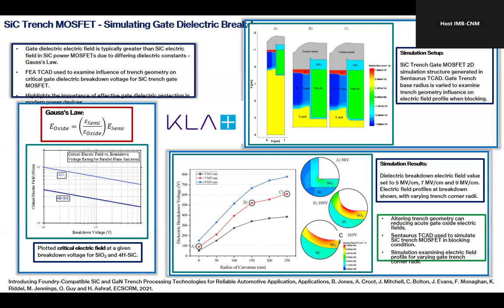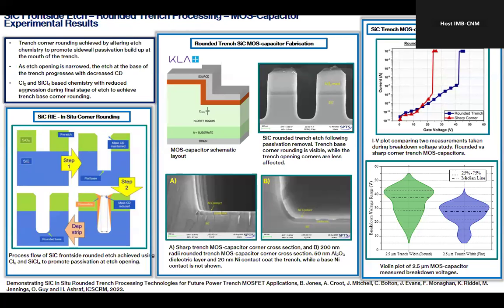So this was a good study, and we backed this up with fabrication. We used our tools to fabricate a nice sharp corner versus a nice round corner, you can see probably this image is the best here. I think we used the deposited oxide in this case, yes, 50 nanometers of aluminium oxide. That's the other thing to note with silicon carbide technology: there's a trend to move towards deposited oxides rather than thermal oxides. On the one hand, silicon carbide's advantage is that it has a native oxide, so you can grow thermally. But the classic approach these days seems to be a few nanometers of thermal oxide backed up by a deposited oxide. That seems to be the way it's going.